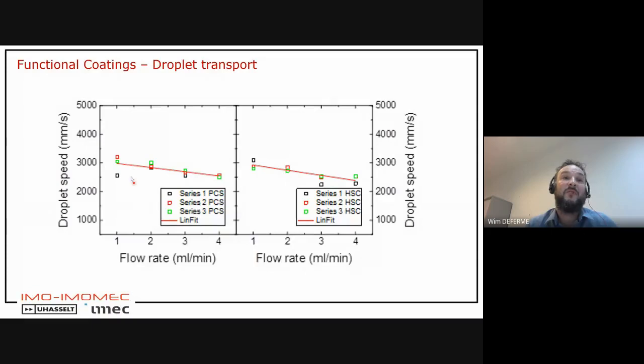We did the same for the flow rate, so the amount of material that you deposit per second or per minute. In this case, it's milliliters per minute, and you see a small change in the droplet speed with the flow rate. The more material you deposit per time, the lower the droplet speed becomes, and you see the same trend in photocorrelation spectroscopy, but also with the high-speed camera.